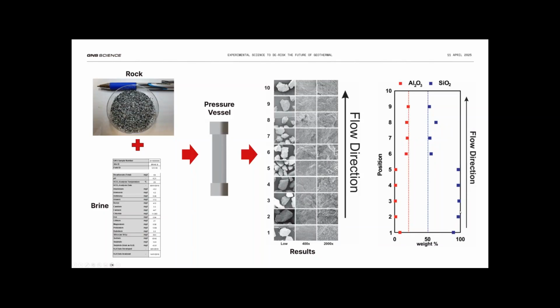We've got over 95% silica on the surface and much less aluminium compared to the unreacted rock. But once we pass position 5, the scaling stops, and the composition of the surfaces is very similar to the unreacted rock. So in this example, what we're seeing is very rapid silica scaling that stops very rapidly. So there's something going on at this position that stops the silica from scaling, probably the reduction in silica concentration.